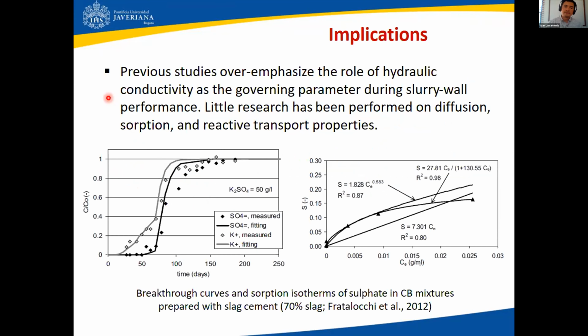Also, browsing the literature on these topics, we learned that definitely there is an overemphasis in previous studies on the role of hydraulic conductivity, which is, of course, a critical parameter. However, for actual vertical barrier performance, it is not the only parameter that takes place. Little research, in fact, has been performed on diffusion, sorption, reactive transport properties, and so on. Perhaps reactive transport has been studied more in reactive barriers, but not in encapsulation barriers.